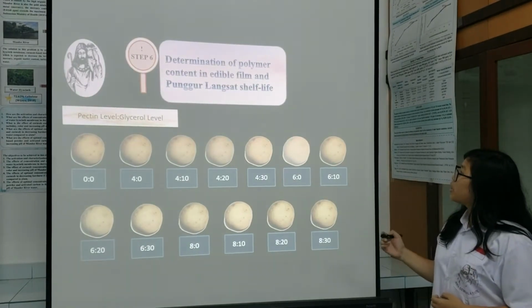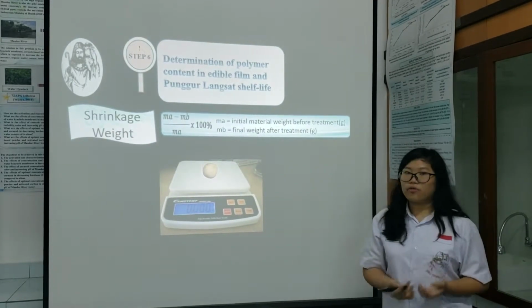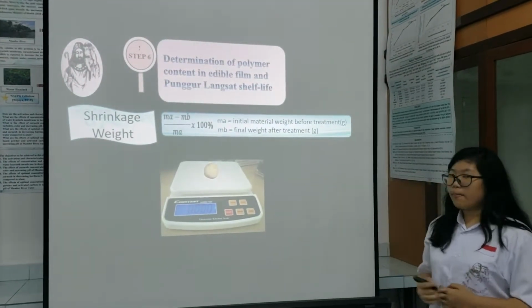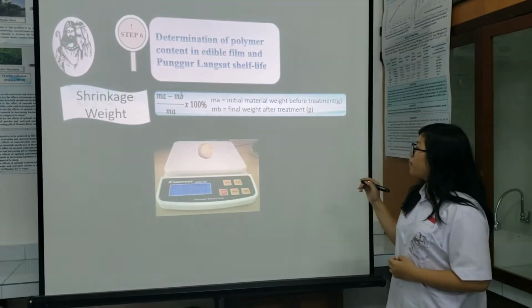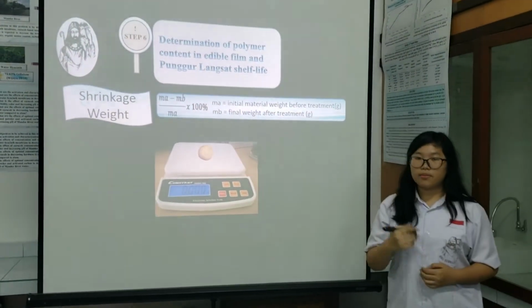Then the determination of polymer content in edible film and Langsat shelf life. Edible film with the variation of Pektin and Gliserol was applied on Langsat, and then the Langsat is being weighed, and we can obtain the physical parameter, which is shrinkage rate by the formula initial weight minus final weight divided by initial weight times 100%.